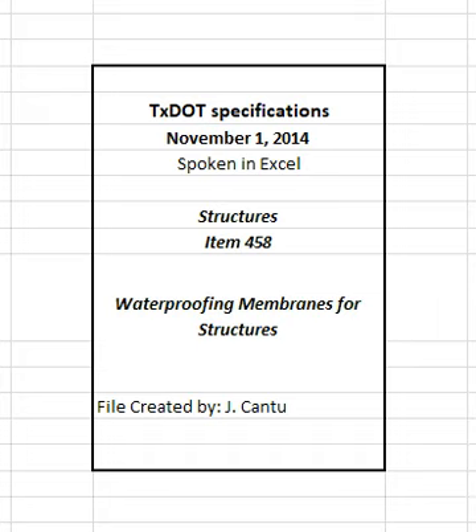3.6 Type 5. Apply waterproofing in 2 coats to produce a minimum cured film thickness of 1/16 inches. Apply using a roller, squeegee, brush, or spray equipment unless otherwise shown on the plans. Apply the second coat within 16 hours after the initial coat. Follow the manufacturer's instructions with regard to the maximum time allowed between coats and any treatment of the initial coat required if this maximum time is exceeded.